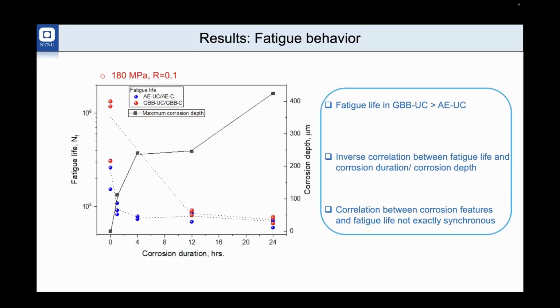Now I'll come to the main result, that's the fatigue. If you see the graph here, I have also superimposed the variation of the corrosion depth so that you can try to correlate how the fatigue life changes with corrosion duration vis-a-vis corrosion depth. With increase in corrosion duration, there is a drastic reduction in fatigue life, especially for a smaller corrosion duration, 1 hour, followed by which there is a sort of saturating trend.